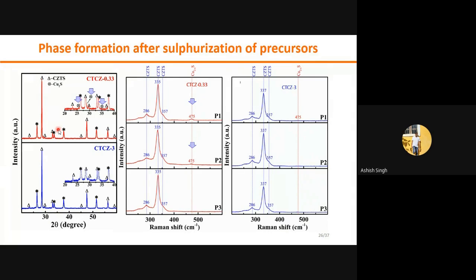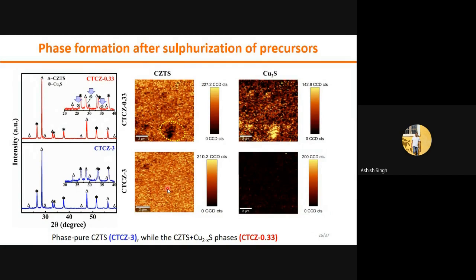For the same samples we used Raman spectroscopy, and we took 3 random points on each sample, named P1, P2, P3 for both samples. We found the copper sulfide impurity phase at points P1 and P2, while this one is giving phase pure CZTS. That means inhomogeneous copper sulfide forms in the CZTS. To confirm that, we performed Raman mapping, and the area selected was 100 by 100 micrometer square, and the scan points were 100 by 100 points in each sample. From this, we found that this precursor gives phase pure and uniform CZTS, while in this condition we observed patches of copper sulfide.